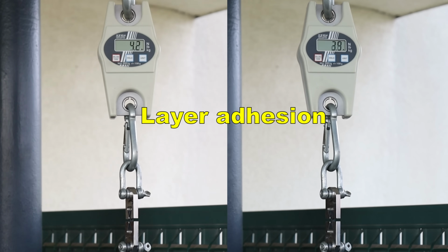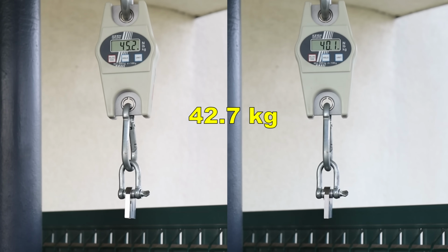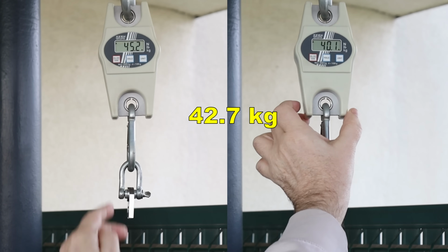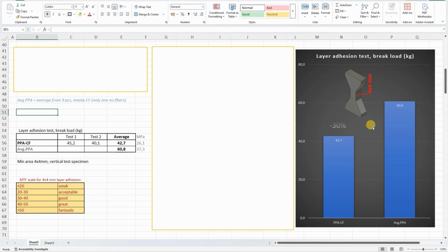Layer adhesion, vertical test specimens. Compared to the average PPA, this filament is weaker by approximately 30%. But look at this table. This is my rating for this size of the test object, and even this is actually great layer adhesion. Only compared to the average PPA or compared to the horizontal object, it looks weak.